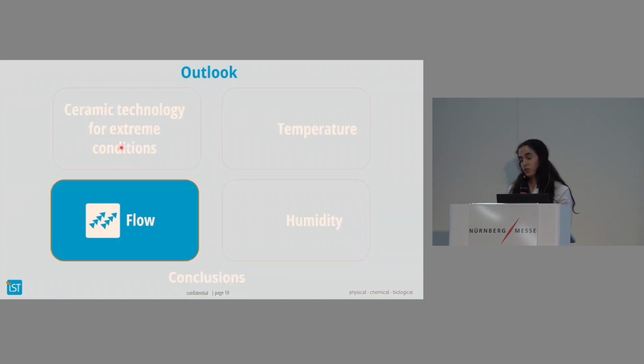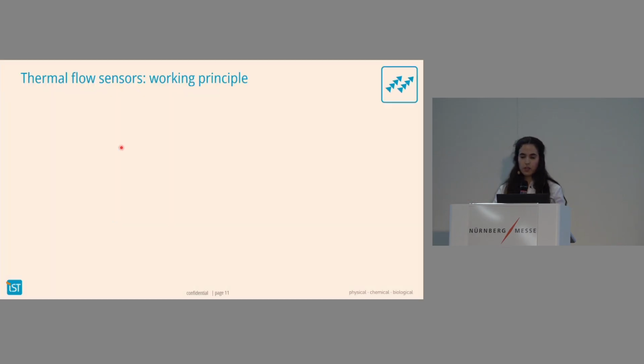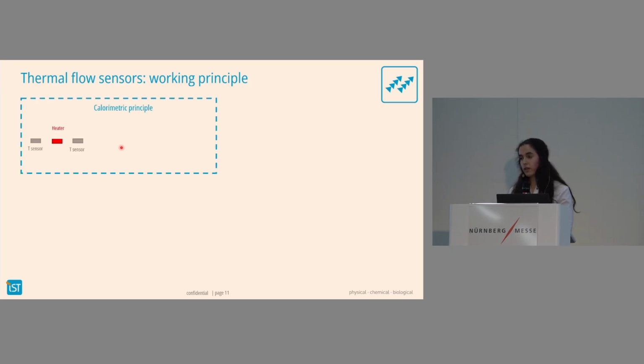So this was about temperature, and the question now is how can we extend this ceramic sensing to flow sensing? For that, I would like to start by explaining the two measurement principles that we use for flow sensing. The first is the calorimetric principle. For that, we have two temperature sensors, left and right, and a heater in the middle. We apply power to the heater, and then when there is no flow, we will have a cloud that is formed on top of the heater. While applying some flow, this cloud would move away from the heater. So while having a constant power, we would measure a different delta T, and this is what we can correlate with the flow to measure flow.